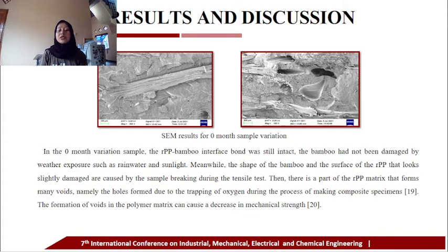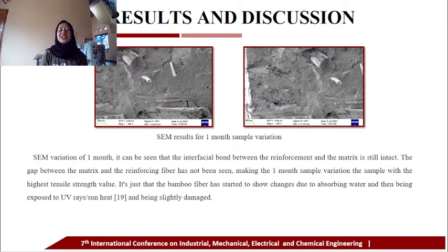Then, there is a part of the recycled polypropylene matrix that forms many voids, namely holes formed due to the trapping of oxygen during the process of making the composite specimens. The formation of voids in the polymer matrix can cause a decrease in mechanical strength. And then this is the result for the 1-month sample variation.